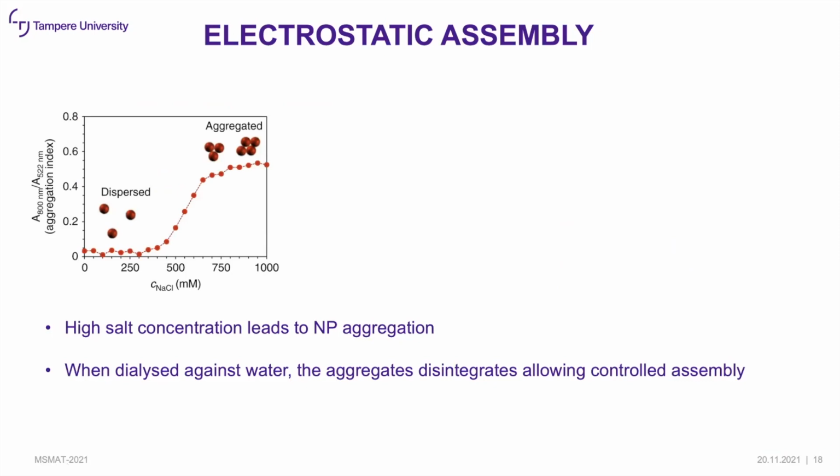Now, with electrostatic assembly, when you mix a cationic and an anionic object, it generally results in random, irreversible aggregation, and leads to what we call kinetically trapped structures. Now we have to avoid such structure formation, and so we decided to approach it differently. If you take cationic particles and add some electrolytes such as sodium chloride, a salt solution, they start to aggregate, but these aggregates are reversible. If you dilute the electrolyte concentration, then you can disassemble them into individual nanoparticles.